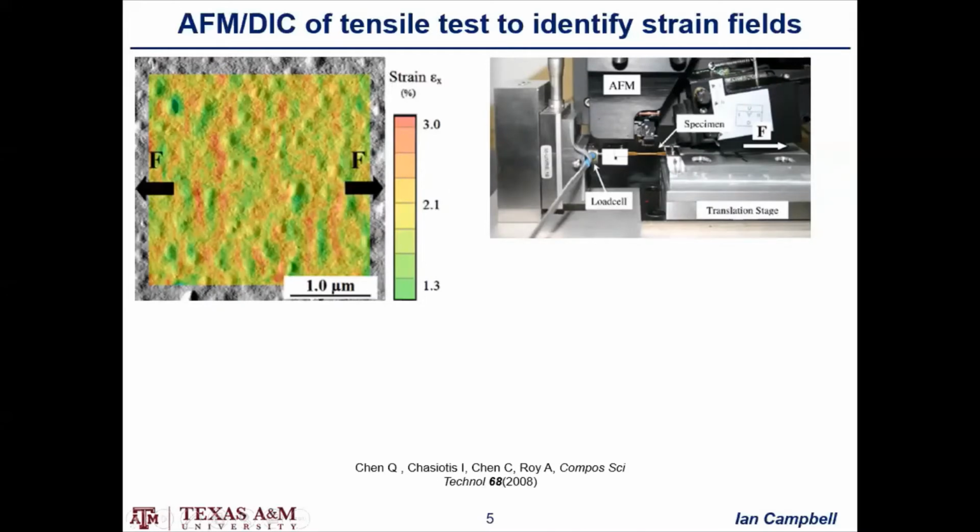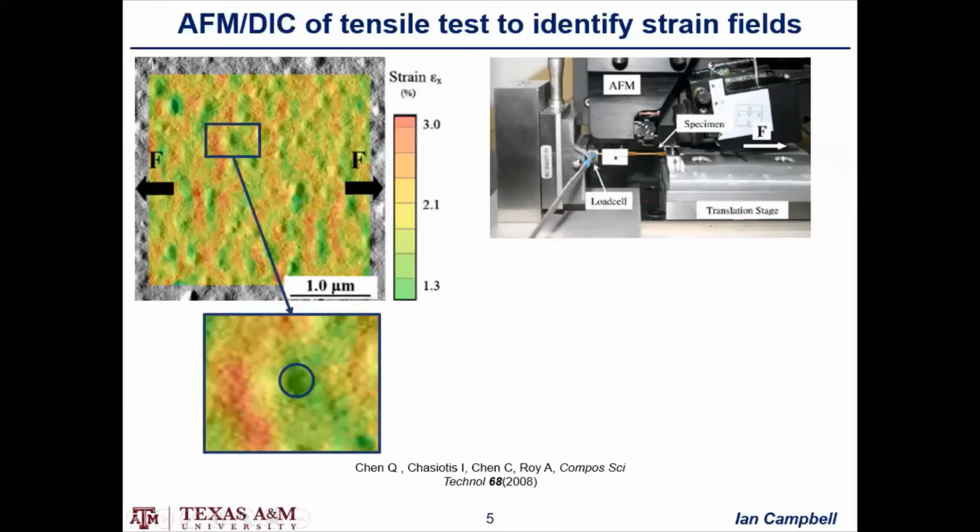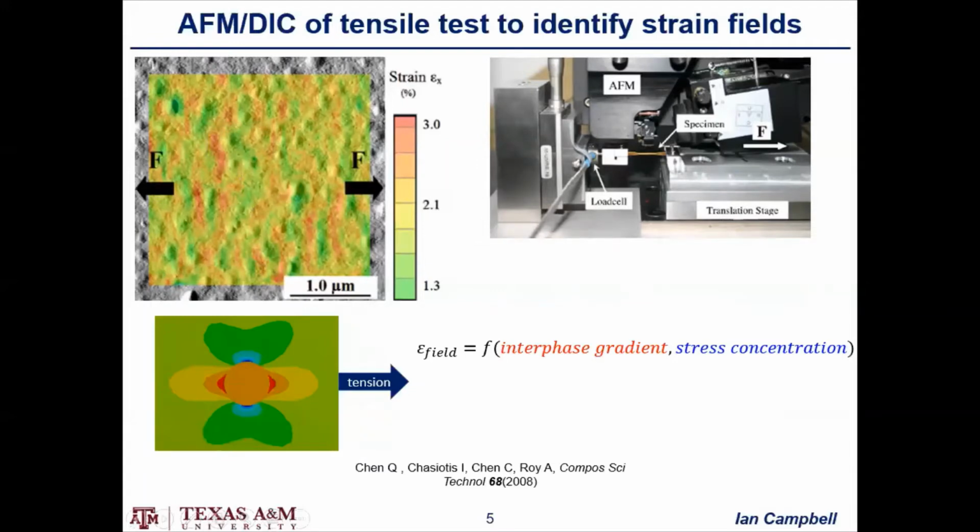In this case, the lack of homogeneity in strain fields around each inclusion is recognizable in the different shading to the right and left of the circled particle. The result was an inaccuracy in the measurement of local mechanical properties. These inhomogeneities can be explained by interpreting the strain fields as both a function of the mechanical stress concentrations around a particle and the property differences across the interface gradient. Determining the interface properties requires the deconvolution of these two factors.